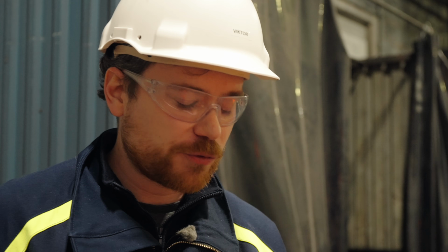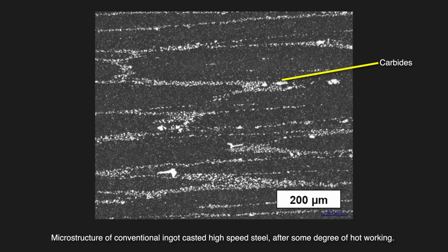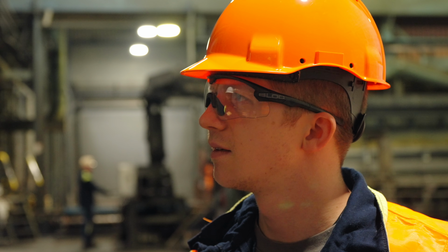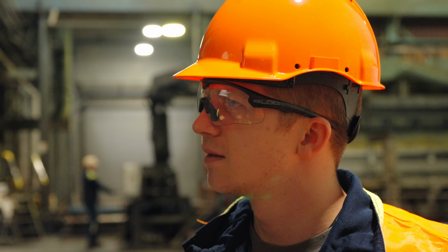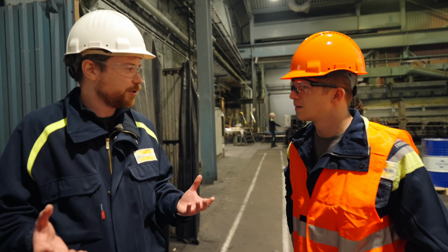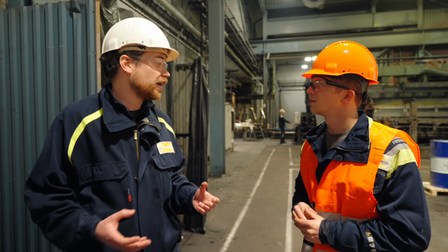So you need to do that to refine the microstructure. Then, of course, it also brings other benefits. The material becomes more tough. You can also hot work it less, because with a conventional ingot casted material, you actually need to hot work it to break up all those carbides within the steel and refine the microstructure. We're actually starting with something that is already refined from being a powder. So we have very little need for the forging from a refining standpoint. We do the forging and the rolling just to work it into the shape that we need for selling it to a customer. But it's not doing a lot for refining the steel in the end.